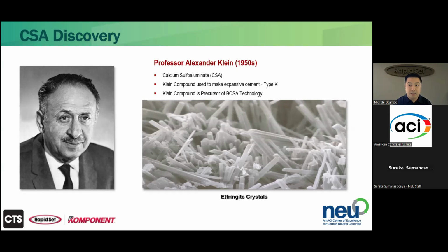I do want to discuss ettringite right now because ettringite in Portland cement is typically associated with destructive behavior. That's so-called delayed ettringite formation, and this is because ettringite forms after the cement has set. And because ettringite is expansive, it creates stresses within that cement matrix and creates cracking.